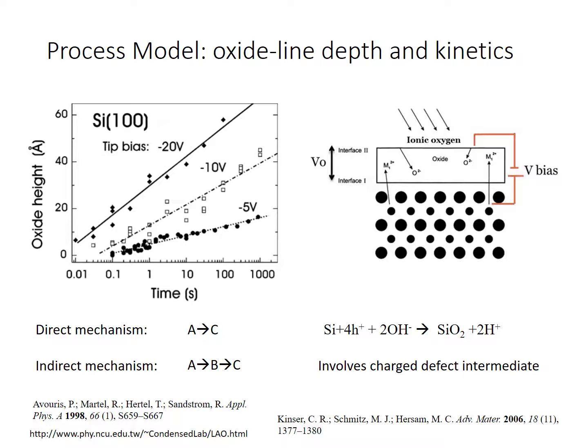The next parameter of interest is the oxide height, or the depth of the oxide into the surface. We can use the Cabrera-Mott model for metal oxidation to determine how the applied voltage affects the oxide depth. In this model, shown in the figure to the right, the applied voltage creates an electric field that enables ions to diffuse through the oxide layer that has initially formed and allows these ions to oxidize the underlying metal. However, when the oxide has reached a critical thickness, this field becomes too weak to lower the activation energy for diffusion, and the oxide becomes self-limiting. Therefore, increasing the applied voltage will increase the thickness for which diffusion of oxygen through the oxide can take place. In the plot shown to the left, we can also see that as the applied voltage increases, the rate of oxidation increases for a similar reason.